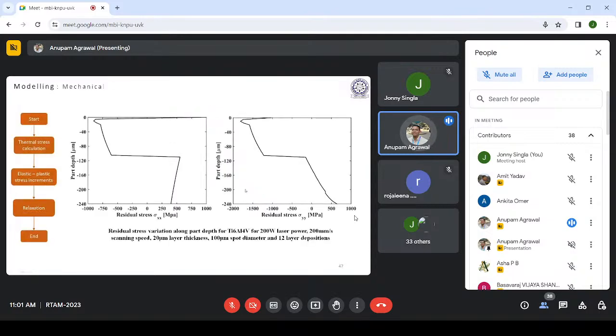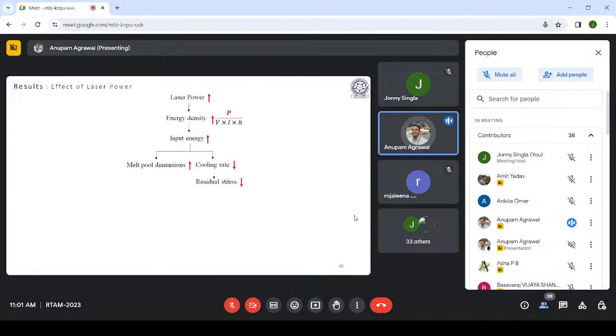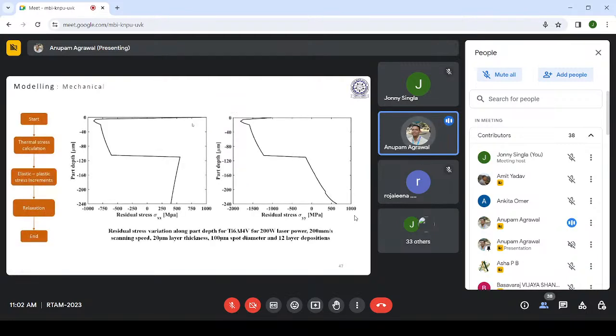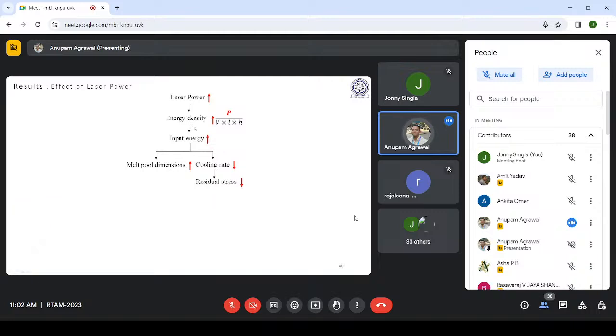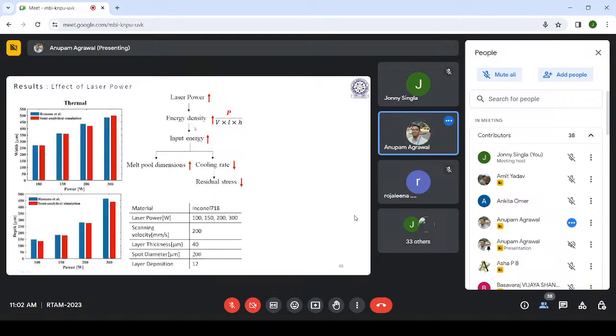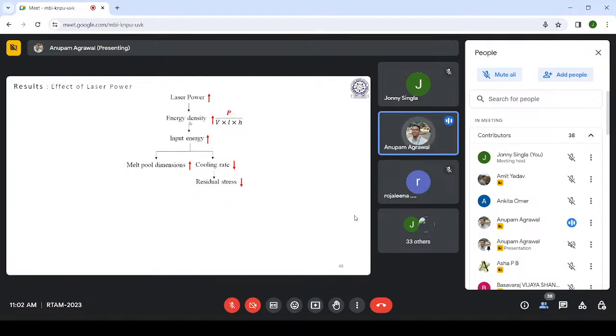With these results, sometimes these numbers may be misleading. What we try to find out is the effect of different process parameters, with our analysis, on residual stresses as well as on the temperature distribution. What we have found is that as the laser power P increases, and the rest of the things are constant, the energy density increases. That means the input energy to any particular location of powder increases. This leads to an increase in melt pool dimensions: length, width, depth. However, the cooling rate goes down, and the residual stresses go down.